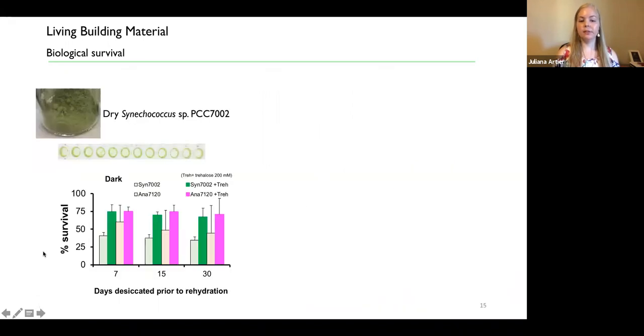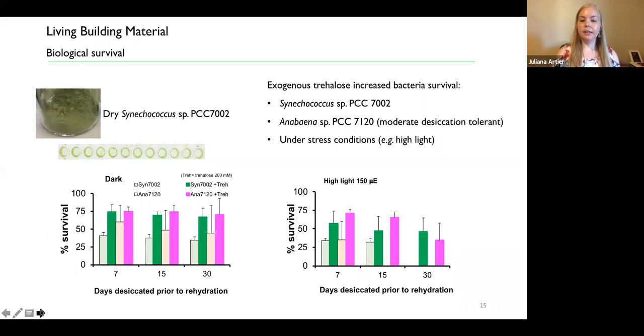And if we compare to another cyanobacteria, Anabaena 7120, which is considered a moderate desiccation tolerant, we can see that simply by adding trehalose here, the darker colors, we can increase the survival of the cells even under 30 days after desiccated. And we can also increase the survival under stressful conditions, for example, under high light. For example, Anabaena 7120 can only survive under very low light, but by adding this simple sugar, we could increase their survival for up to 30 days. So this was something we later introduced in our living building material.